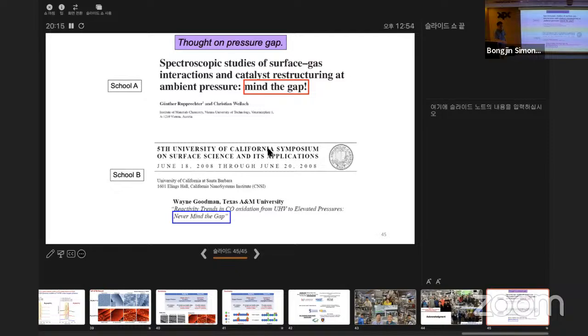I can show you some of the data of the CO2 experiment that we did. We prepared CO2 on platinum 111 and copper 111, exactly the same thing. 1,000 Langmuir, no changes. 10 to the minus 6, no changes. 10 to the minus 5, no changes. When you introduce 1 millitorr, you start to see the changes, and we don't know why. The only thing that explains CO2 dissociation on this surface at the moment is the molecule being squashed on the surface, creating band structures, and then getting more charge transfer from the surface and being dissociated.